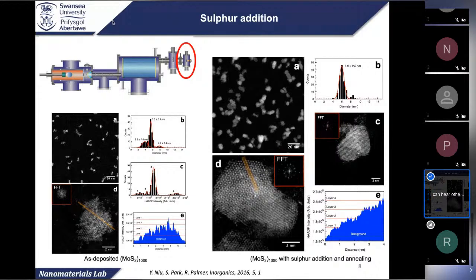After sulfur addition, on the right-hand side, these are the images showing the clusters after the sulfur addition and the annealing. From the diameter distribution, you can see there's only one peak left, which is around 6 nanometer. Basically, this comes from the peak of 5.5 on the left-hand side. So when you give the extra sulfur, the cluster becomes bigger, and the broken-down clusters connect into one cluster. They just rejoined.